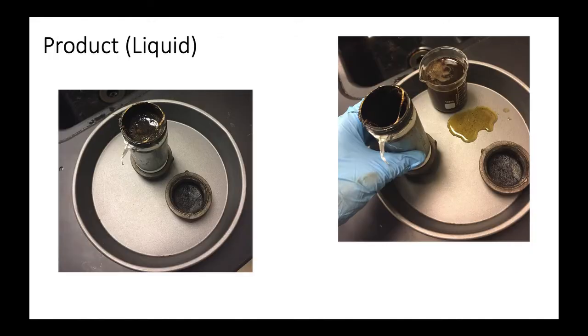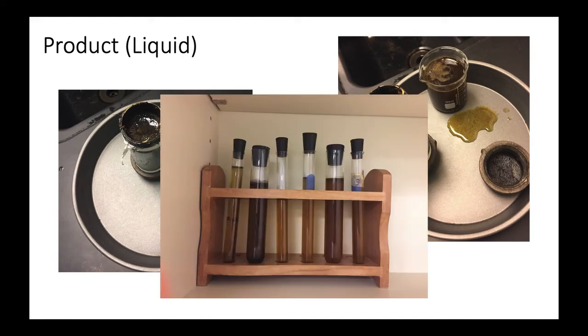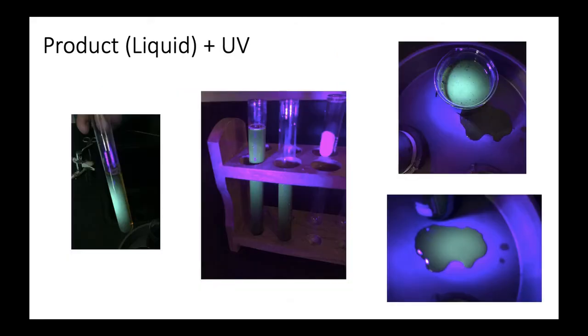By the second run, the inside of the reactor was considerably corroded and was responsible for the dark particulate that you can see in the spill puddle, in the beaker, and the inside of the pipe. I tried diluting some of the solutions, which made more concentrated test tubes darker in normal light, but this did not have a detectable impact on the luminosity of the quantum dots under UV, as you can see in the center image with the two different test tubes.